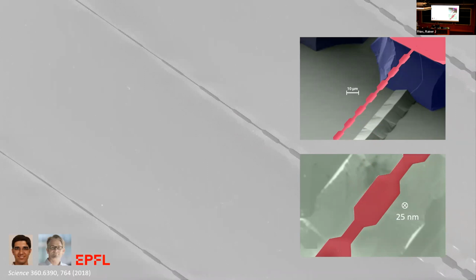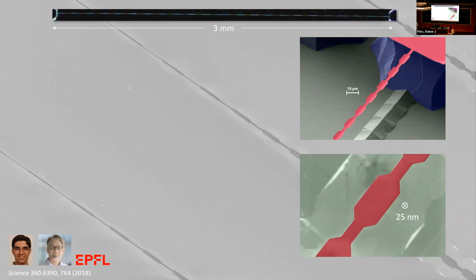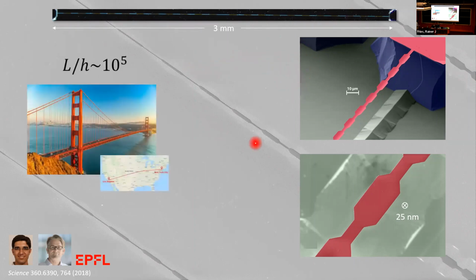It's a thin film of silicon nitride glass. Another thing you can't see really is the length of this object. So this is a stitching of several images in an optical microscope. This particular device is around 3 millimeters long. We made significantly longer devices than this. But if you calculate the aspect ratio of this beam, it's around 10 to the 5. And actually, back in 2018, that was the highest aspect ratio mechanical device ever made. It's on the order of the other competing devices, which are sort of graphene sheets. And to get a sense of scale here, this would be akin to building the Golden Gate Bridge from Los Angeles to New York.